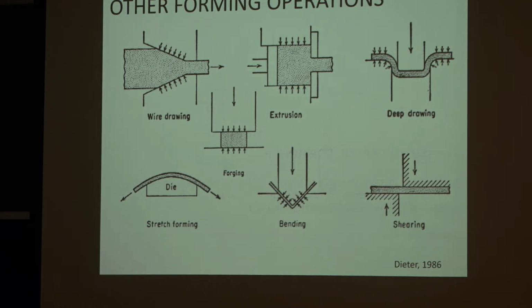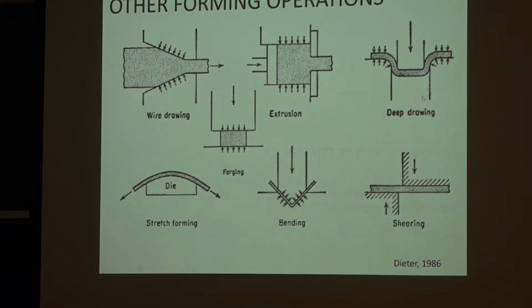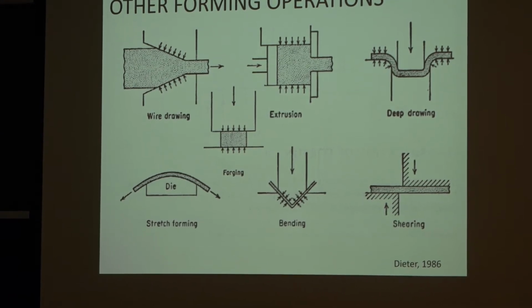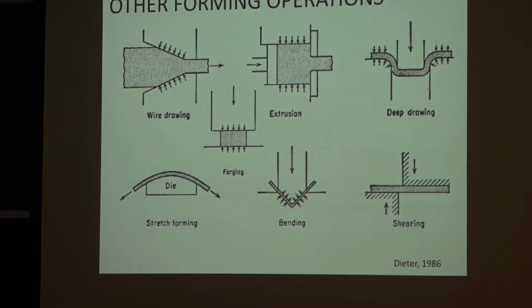Deep drawing is also used for aluminum a lot to make the Coca-Cola or Pepsi cans. So here you start with a flat. It's the upper right, and as you deform it, you need a lot of work hardening into that aluminum, so the edges here don't thin down and break. So it's a little bit the same effect in the last class when we talked about necking in tension. You do have tension going on there. So the type of aluminum that you need to make a soda can is very, very specific, and even in terms of the orientation of the grains that allow you to get sufficient work hardening so you lose your thickness in some of the areas.